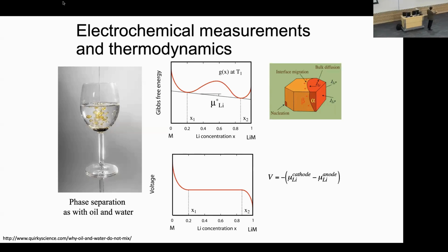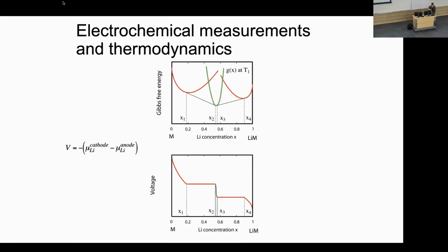And because of the Nernst equation, you can see this directly in the voltage curve, because the Nernst equation tells you that the voltage is related to the chemical potential, which is equal to the slope. And when you're inside this two-phase region between X1 and X2, your slope is constant, and so you get a constant voltage, a plateau in the voltage. So whenever you see a voltage curve like this, where you get a plateau, you know something like this is happening in your cathode material. You're going through a two-phase reaction.